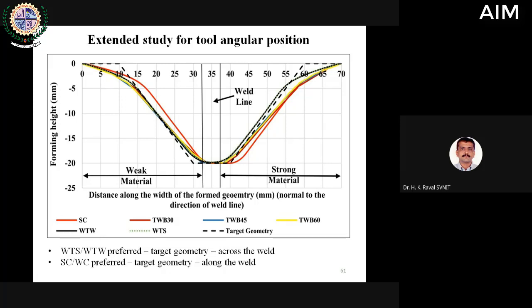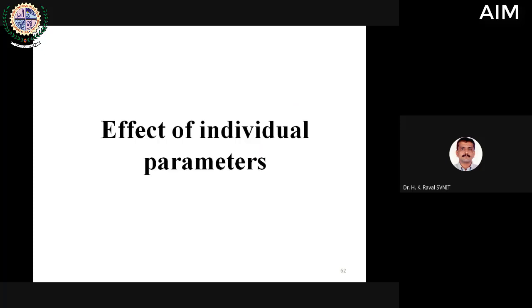So that is giving us very useful information that to control the geometry accuracy, one should decide the starting position not strongly on the center, neither on a strong center or weak center, nor even on the weld line. It should be at a certain angle that will give you better performance, or your measurement should be at certain sections, and should not be a section aligned with the starting point. So that was the study of the geometry accuracy.